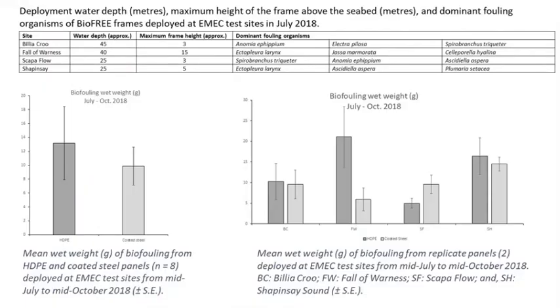So a few stats to show you. Again, this is very, very preliminary at this point. We have deployments occurring in 4 different sites, the 4 different wave and tidal sites, and we've identified the dominant fouling organisms in those different sites.